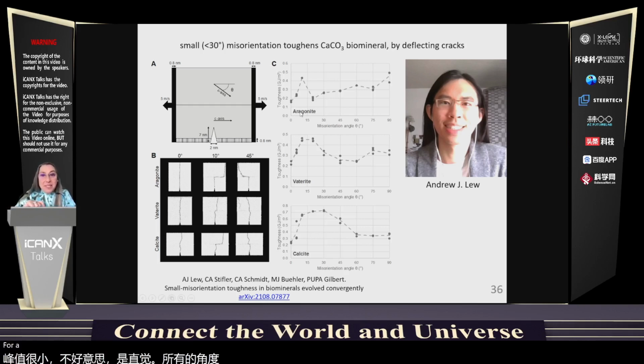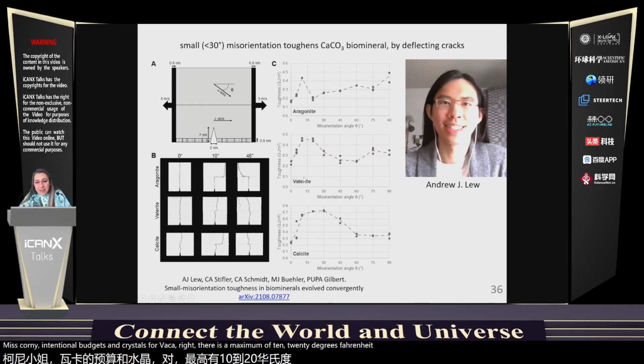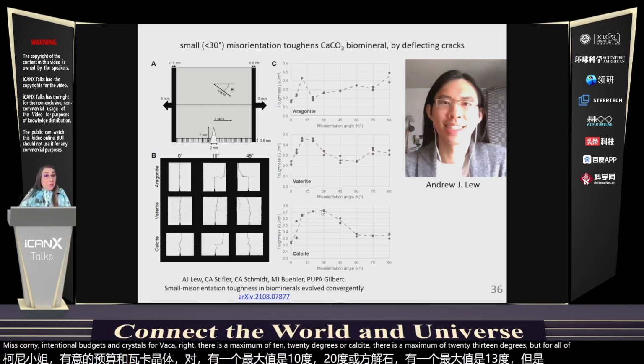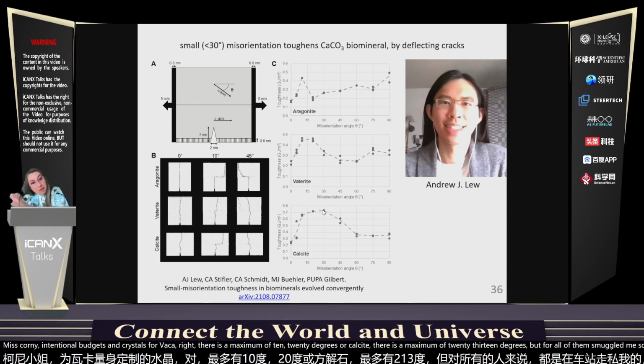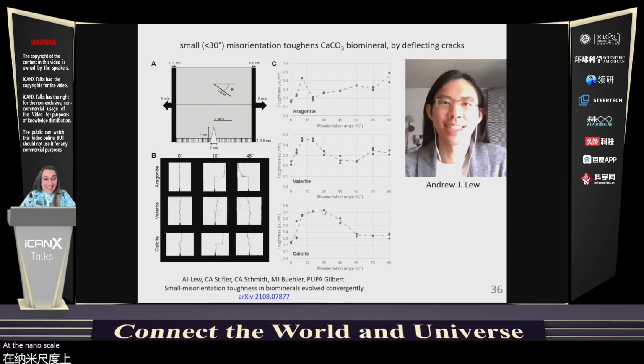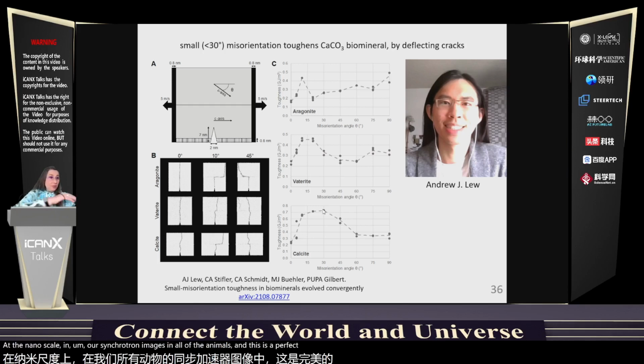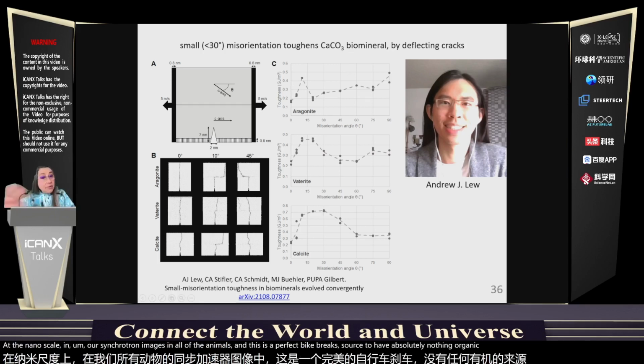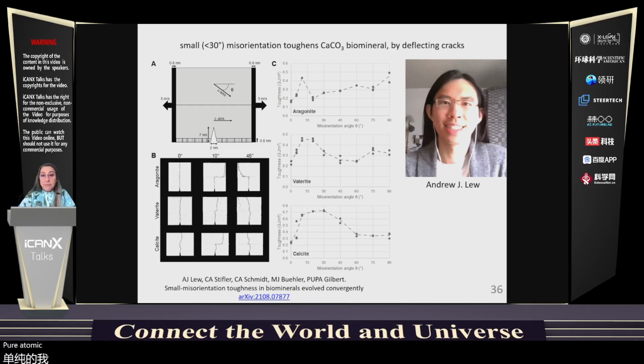For aragonite, we see that there is a maximum at 10 degree misorientation of adjacent crystals. For vaterite, there is a maximum at 10-20 degrees. For calcite, there is a maximum at 20-30 degrees. But for all of them, small misorientations, which corresponds perfectly with what we observe with PEEM mapping at the nanoscale in our synchrotron images in all of the animals. And these are perfect bicrystals. They have absolutely nothing organic, absolutely nothing biological in them. They're just pure atomic systems.